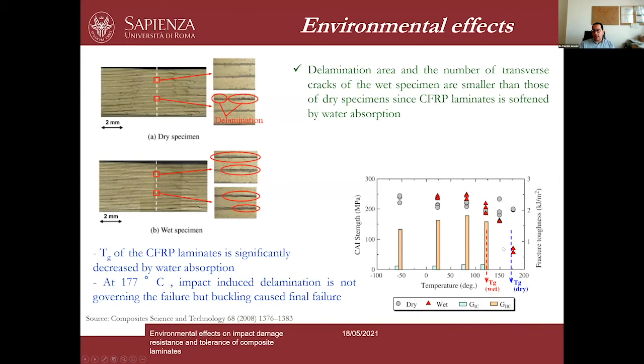What we can see here is that at this specific temperature, the wet specimen behaved in a completely different way compared to the dry specimen. And the behavior was significantly reduced. Okay, why did this happen? This happened because actually in this specific case, this temperature was higher than the glass transition temperature of the wet epoxy matrix. Okay, so in this case, the damage mode was completely changed by the water absorption, and in particular, it was no longer the impact-induced delamination to control the failure of the composite material, but instead it was the buckling.